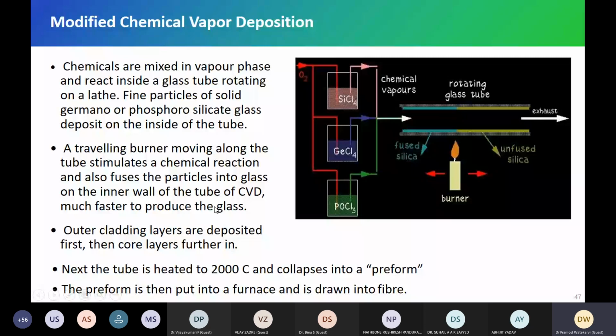But currently the industries don't use MCVD. Some companies are using it, but if you are looking at millions of kilometers per annum, MCVD is of no use because of the size of the tube. It is limited to 25, 30 or 40 mm diameter. And we are looking for 200 mm, bigger diameters, so that we can manufacture more and more fiber to cater to our customers.